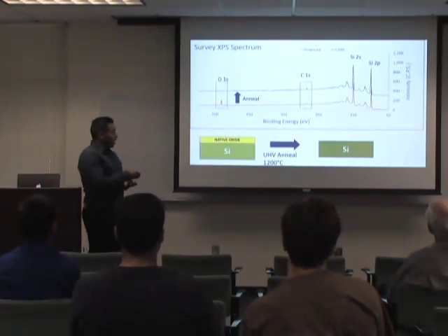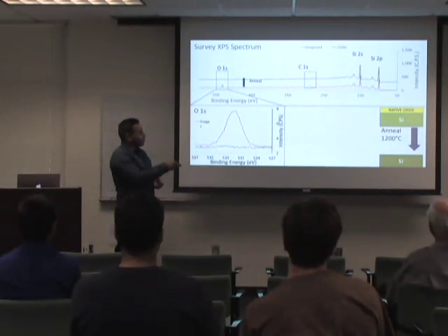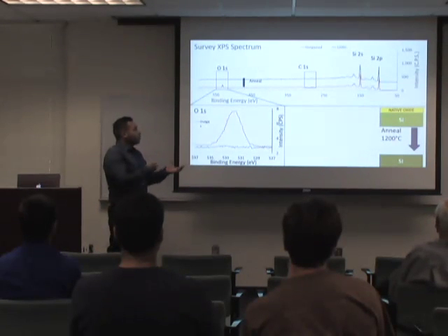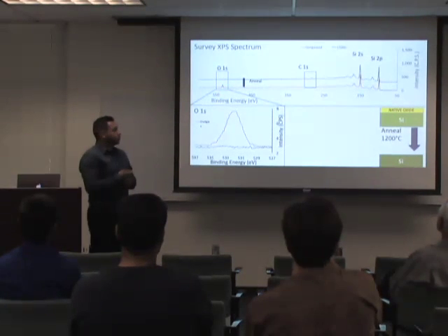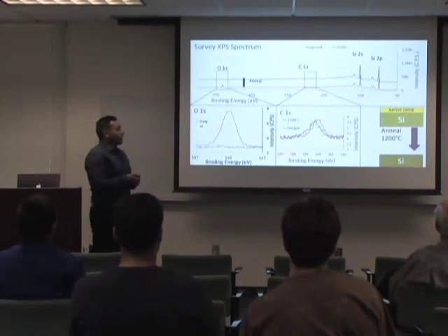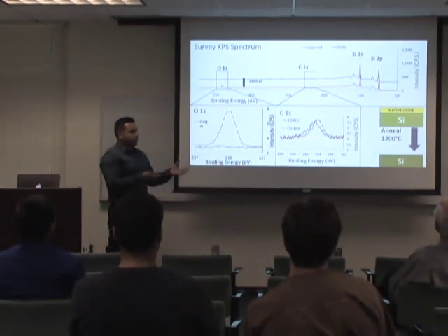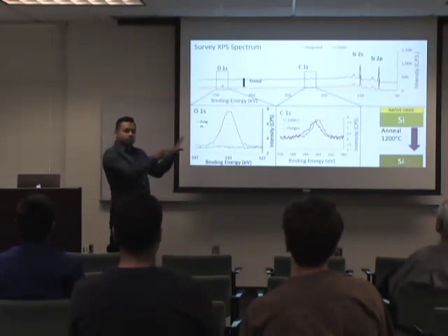in the sample. So after anneal, we know that we almost get all of it. We actually take out all the oxygen. In this case, what we're looking at is the peaks that give the spectrum. But for carbon, we're not able to remove all the carbon in this example. This is just to let you know how we read the XPS.